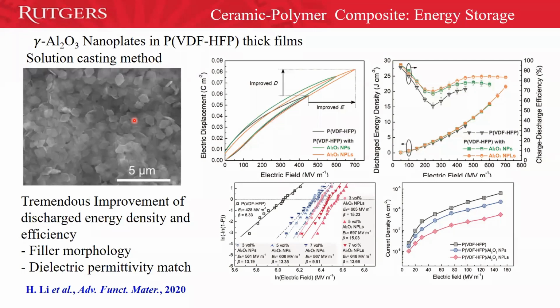And the idea here is to match dielectric properties of the filler material with the dielectric properties of the polymer material. So the polymer matrix is PVDF. Now here the filler is alumina nanoparticle, alumina nanoplate, and then this is the PVDF property itself. You see that by going to the alumina nanoplate, you can improve electric field strength as well as electric displacement quite impressively from pure PVDF to a very highly loaded gamma aluminum